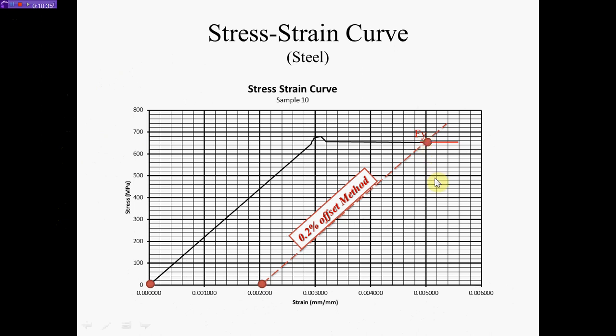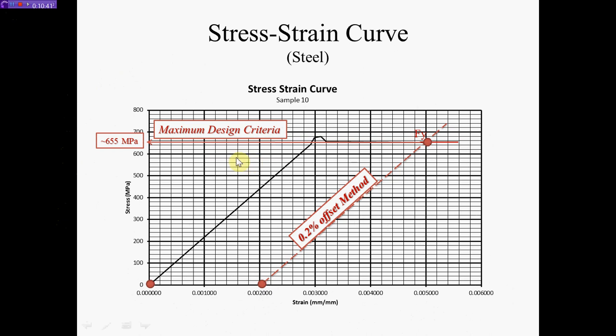Now I have to go and find my yield stress. All I need to do is pick it off the y-axis. Going over right here, I'm going to pick it off as approximately 655. The graduations in between are 20 each, so there are five graduations — 20, 40, about 55. So our yield stress is 655 MPa. We know that when designing, we should not exceed 655 MPa.